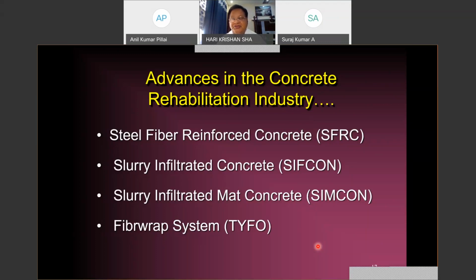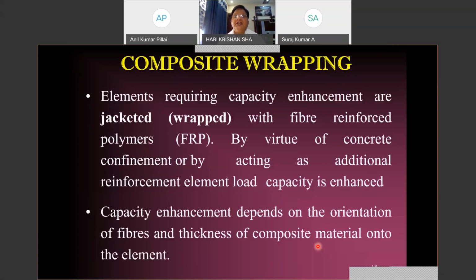Then came into existence the fiber wrapping system. And this fiber wrapping system, using fiber reinforced polymer, is the current basis for the retrofitting of distressed structures. As far as composite wrapping is concerned, friends, the elements requiring capacity enhancement are jacketed or wrapped with fiber reinforced polymer. By virtue of concrete confinement or by acting as additional reinforcement, the load carrying capacity is enhanced. It is a very simple method, wherein the distressed structure is wrapped from all around, and because of the confinement of concrete, the load carrying capacity is enhanced.